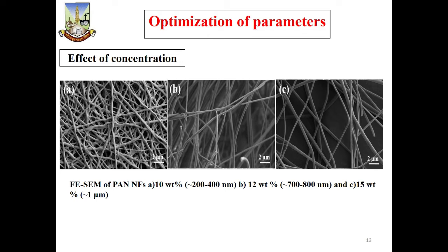As I mentioned, the different parameters are very much important. When these parameters are concerned, take the effect of concentration, that is, the viscosity of the solution. This is one example which I have put here, where we have drawn this fiber in our laboratory, PAN nanofibers. When concentration is 10 weight%, fiber can be drawn in between 200 to 400 nanometer. When concentration is 12 weight%, the fibers are drawn in between 700 to 800 nanometer. At 15 weight%, 1 micron size. From this study, it has been observed that at minimum concentration level, the size of the nanofibers is very small, and 10 weight% is found to be the best concentration for drawing of the fiber, with a fiber size of 200 to 400 nanometer.